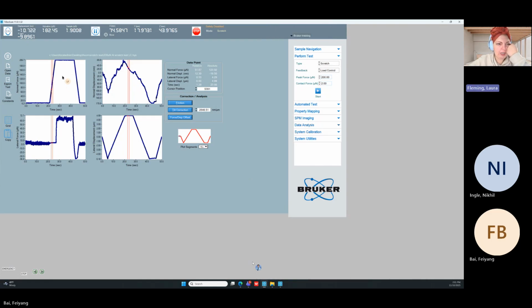So we know that these are correct, and our lateral force was also measured correctly, but this normal displacement is difficult. If we look at this graph, I'm going to grab these bars and look at this segment first. You can see that the bars are updating on the other graphs as I navigate. They match here and they match here.